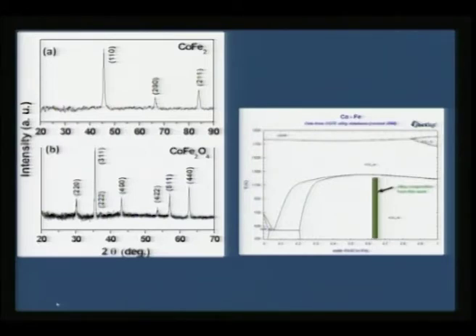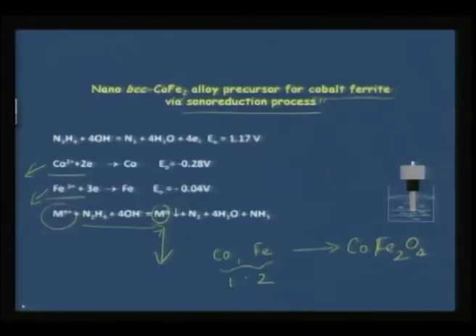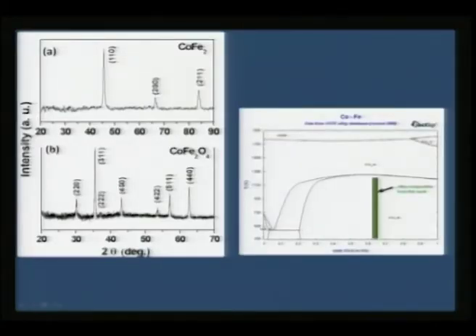As you would see from these two X-ray patterns, interesting things happen. Now, when you take the cobalt and iron salt and when you try to reduce it, instead of passing oxygen, if you are going to do this in argon atmosphere and if you are going to change to oxygen or air, you can see the corresponding end products are not essentially the oxide. For example, if you bubble it in argon atmosphere, the X-ray pattern that you get is peculiar and it is quite different from what we expected as CoFe2O4.